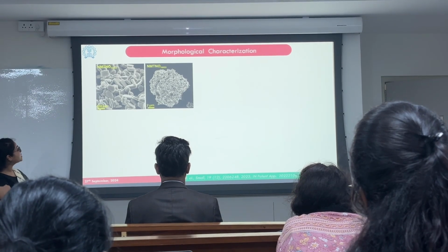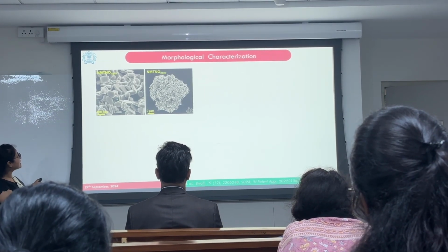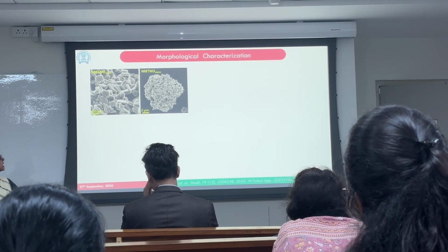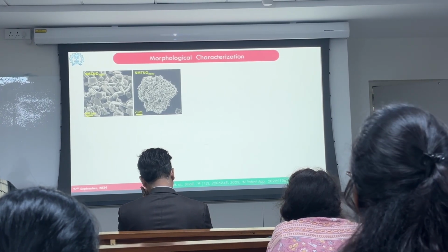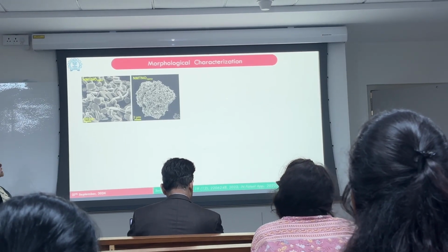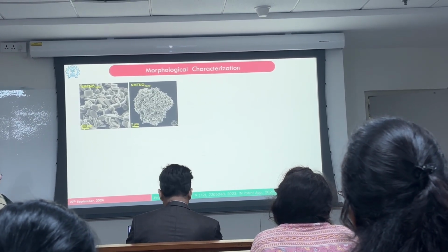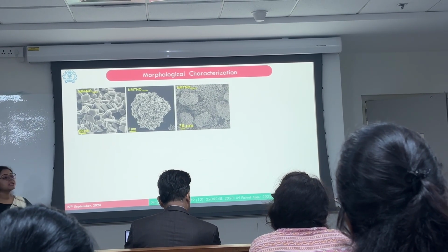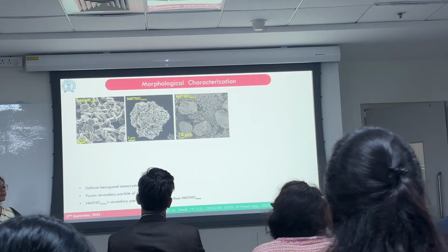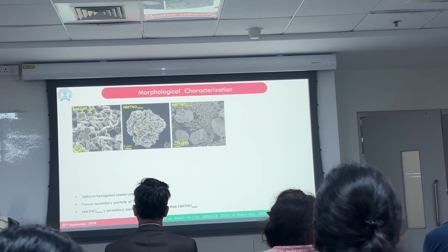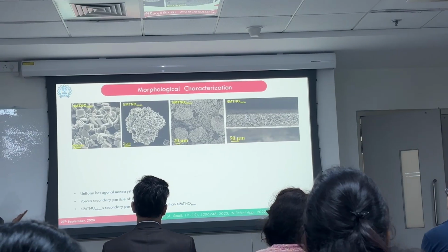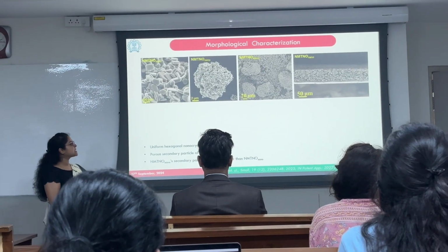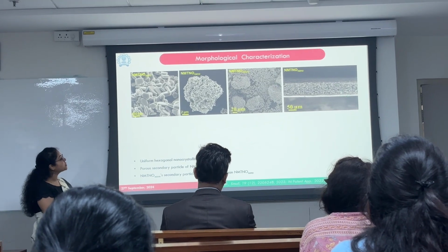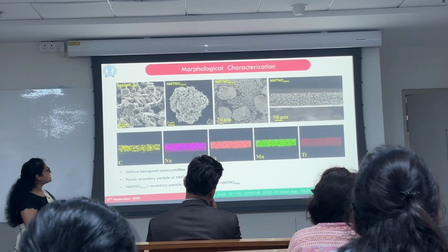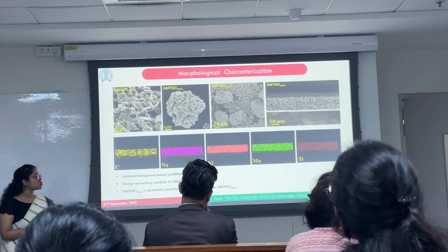Further, we analyzed the morphology through scanning electron microscopy, and through the SEM micrographs, we can see that the primary crystals are almost hexagonal, plate-like structures with clear facets and uniform geometry. As we had hypothesized, the secondary particle formed out of the nano is quite porous in nature, in contrast to which the NMTNO micro gave us a bigger particle, around 5 times bigger than that of the nano, and also quite non-porous in nature.